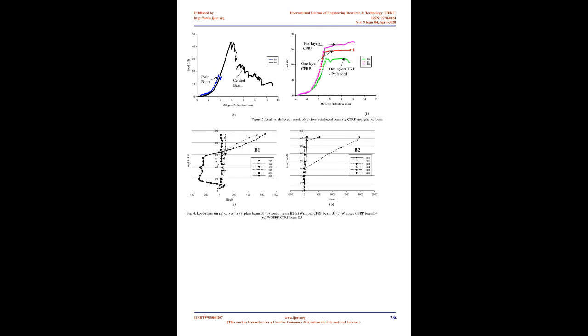The SG1 and SG6 strain gauges were located in the shear span. As shown in Figure 4C, the strains in SG1 and SG2 exhibited a steep increase after a load of 42 kN. The strain gauge SG5 recorded a steep increase in strain around the experimental peak load, which suggests that failure occurred around the location of this strain gauge.